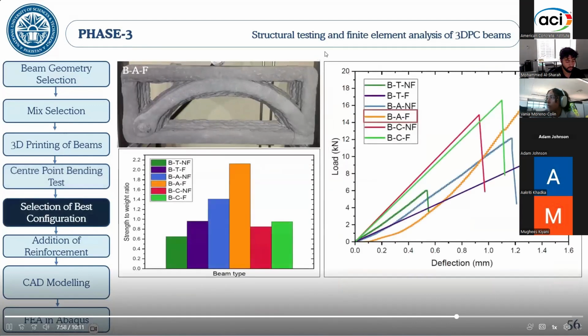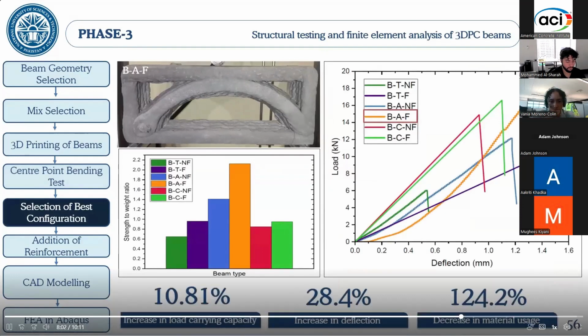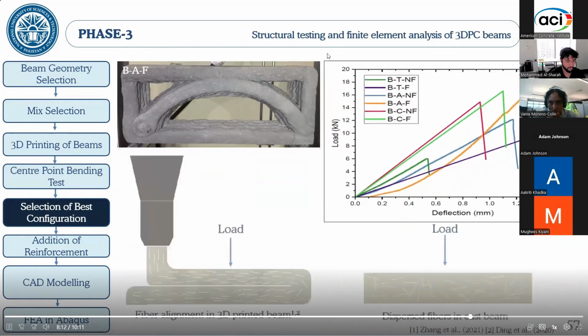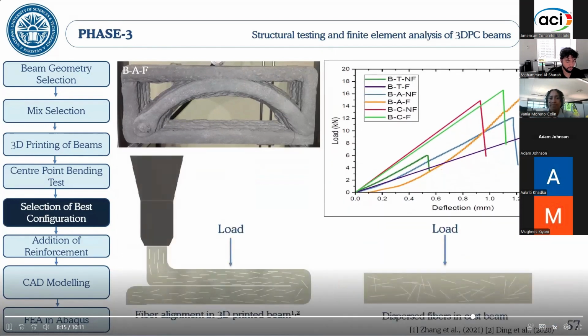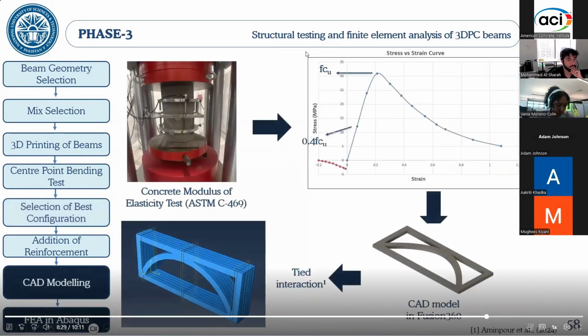Based on the experimental results, we chose the arch fiber beam as the beam with the highest flexural performance, having a 10.81% increase in the load carrying capacity and a 124.2% decrease in the material usage as compared to the cast beam with fiber reinforcement. This exceptional increase in the flexural strength of the arch infill beam can be attributed to the high degree of fiber alignment observed in 3D printed beams as opposed to a cast beam in which the fibers are randomly dispersed.